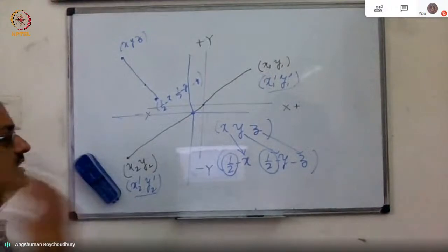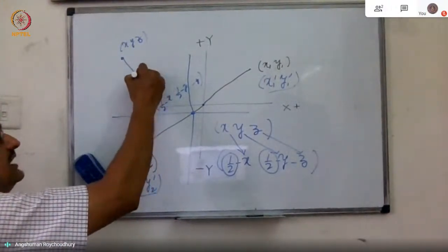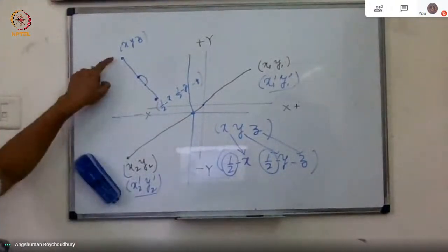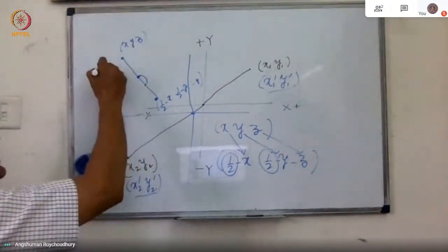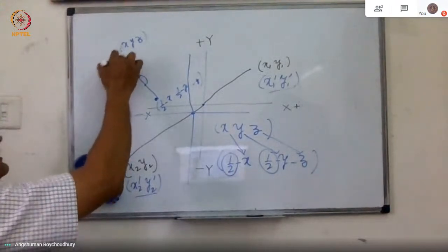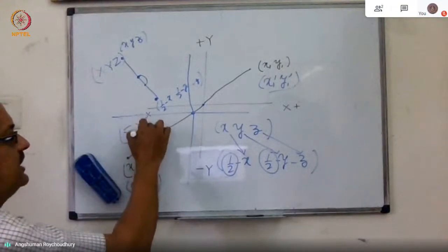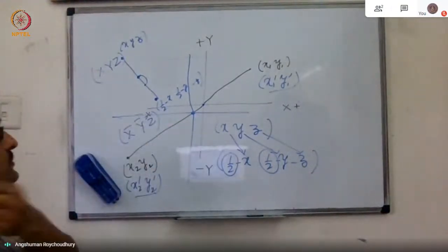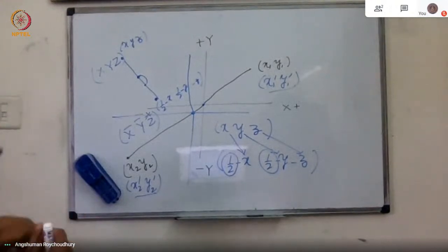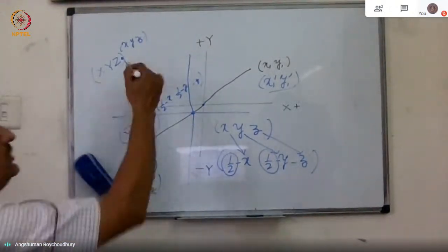So now instead of this origin, if we shift the origin to some other place, then we will have a new set of coordinates which will be x, y, z and x bar, y bar, z bar. So these two coordinates will then be centrosymmetrically related with respect to the new point.